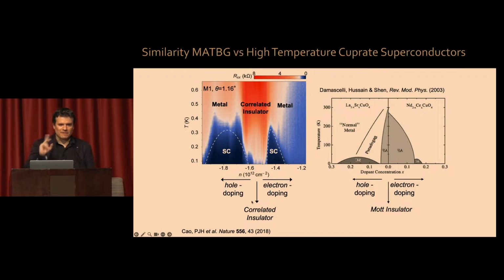Okay? Now, there's a big difference between these 2 diagrams. This thing is a theoretical phase diagram. Meaning, in order to populate this plot with actual experimental data points, you have to grow hundreds of crystals, each with a different chemical composition, because not all materials grow, for electrons and for holes and for different compositions of electrons and holes. Whereas this plot that is here is a real experimental plot. In one device, I just dial a knob, and I can go from here to here and build this plot in a few seconds, okay? In a single disordered realization without having to grow multiple samples or devices. So that obviously is something that is advantageous to study the properties of these materials.